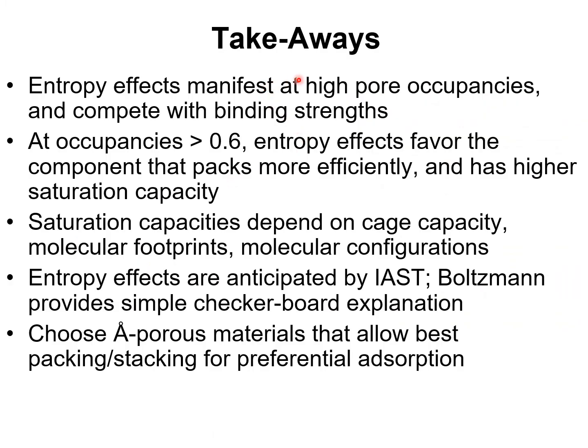The important takeaways from this presentation are summarized on the slide. Entropy effects manifest at high pore occupancies, and entropy effects compete with binding strengths. Often, the entropy effects are so strong that they can override and overturn the hierarchy of selectivities dictated by binding strengths.